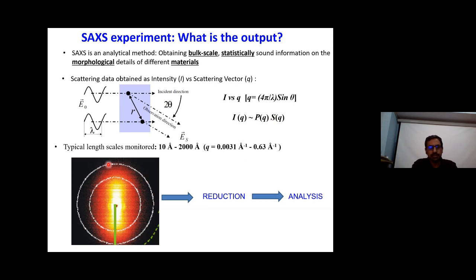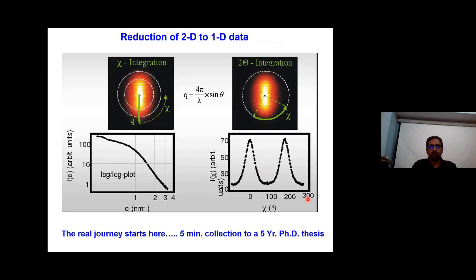So this is how scattered data looks like. This is a particular image which has come onto the detector. You can see these yellow and red rings. Now you take this data, you do the reduction and you do the analysis. What do you mean by reduction? This is actually a 2D scattered radiation. You have to convert it into 1D. 1D data means you have to integrate. You can do either chi integration or 2 theta integration. It's not important right now to understand much, but generally people do this 2 theta integration.